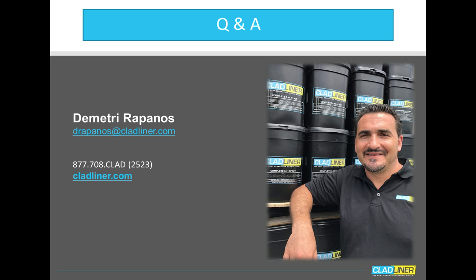How easy is it to use a rebuilding mortar under Cladliner? It's a simple process because Cladliner, at the end of the day, as we said before, marries epoxy with cement. So essentially, you almost have a primed cement that you're applying. So if you think about it this way, what we have is a very good bond between the two cementitious products. As I mentioned in the case study before, the one in Brunswick, Georgia, if a high-quality approved resurfacing cement is wet applied to the surface, it does not have to cure fully before the epoxy modified mortar is added on the top of it. It can be added on top of it as soon as it is firm enough to accept the pressure of the trowel.